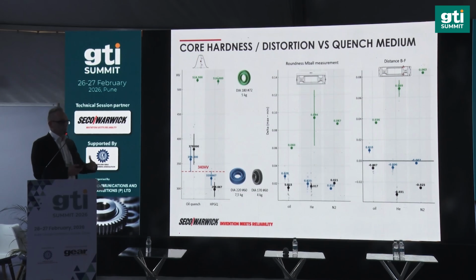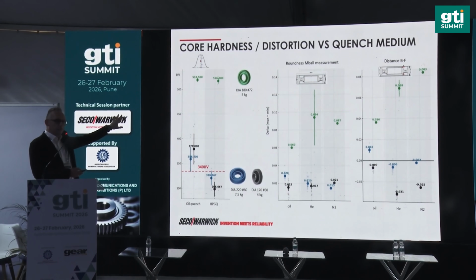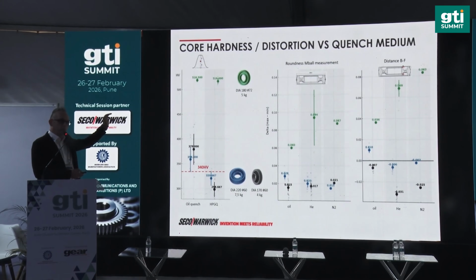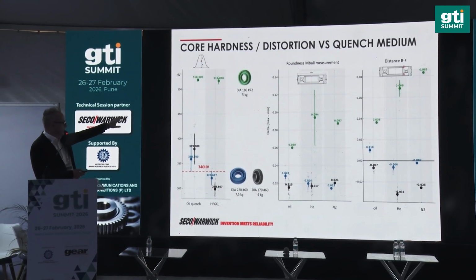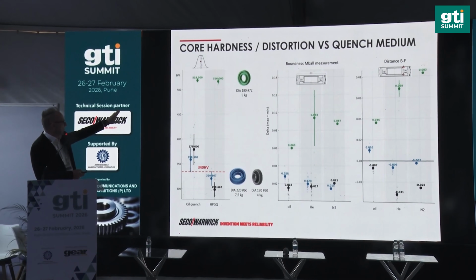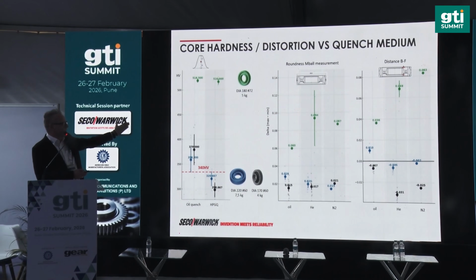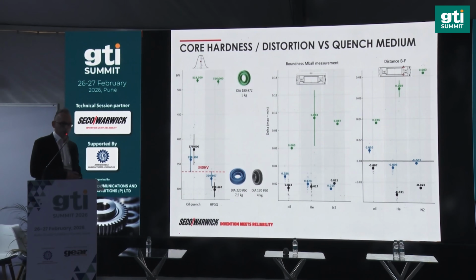And of course, due to the different quenching methods, we will discuss a different level of distortion. However, as you can see, the green points refer to steel at a very high hardenability level, and for the purpose of meeting the core hardness, it doesn't make a difference whether you go with oil or high pressure gas quenching. In both situations you can actually meet it. And if you transition to high pressure gas quenching, you can get all the benefits by optimizing the gas pressure in order to minimize the distortion.